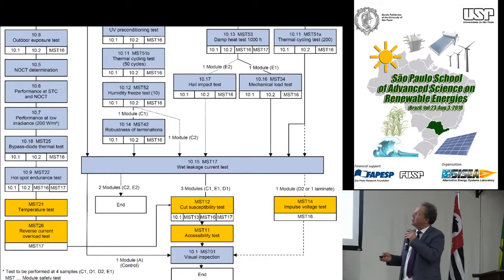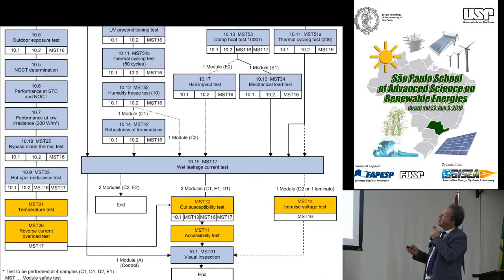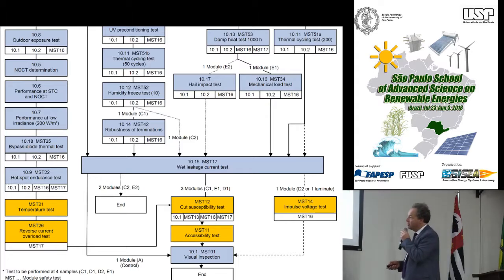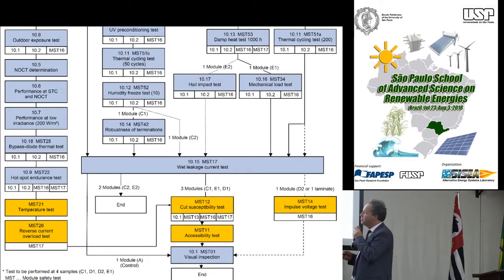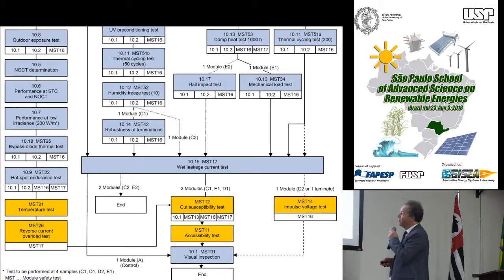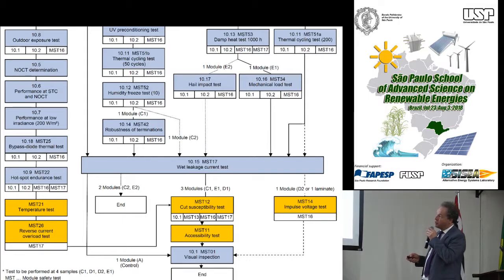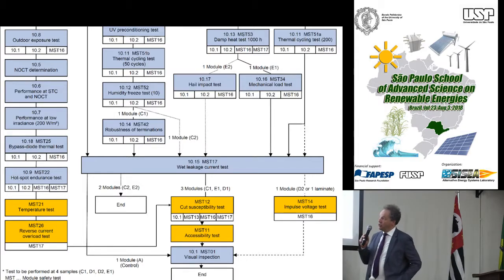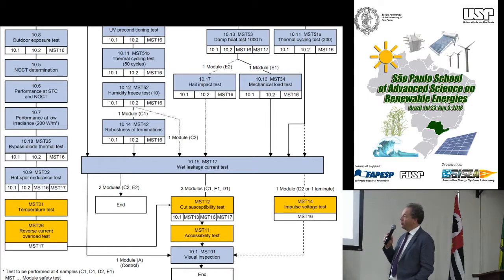Come to the second part here. This is the other parts of the thermal cycling, and then robustness determinations. Here you see the bypass diode tests. So you see whether the bypass diode is strong enough really to survive even a load which is 25% higher than normal load. A hotspot endurance test. So you see whether, if you shadow one cell, it's causing such a high temperature that the cell will burn.